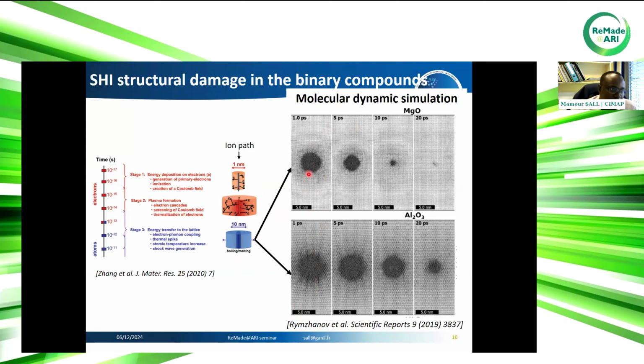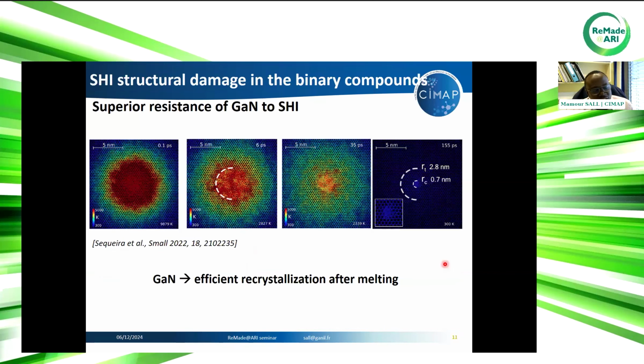What we can see from this simulation is that 20 picoseconds after the melting of the material, in both materials, MgO and sapphire, the remaining disorder in MgO is very low compared to the one in sapphire. This means that after the melting of the material, there will be a material-dependent effect on track creation. In fact, in MgO, we have efficient crystallization of the melted region. This is not the case in sapphire. Why I'm talking about this is that gallium nitride, in fact, behaves exactly like MgO.